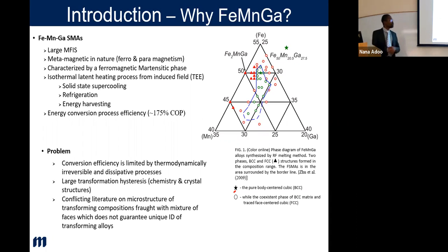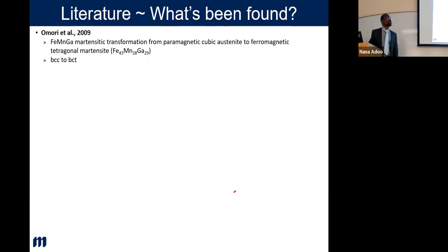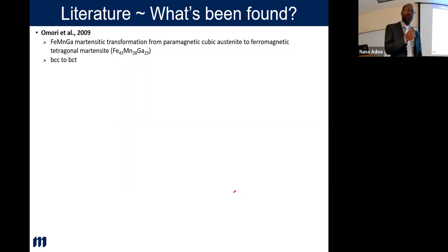So this served as a very good stage to start my work from, and I'll share what I've been finding out so far. With respect to other works which have been done, since 2009, Omori and his group found out that in these iron manganese alloy materials, the transformation was actually from a BCC to a BCT, which guaranteed your phase transformation to go on.